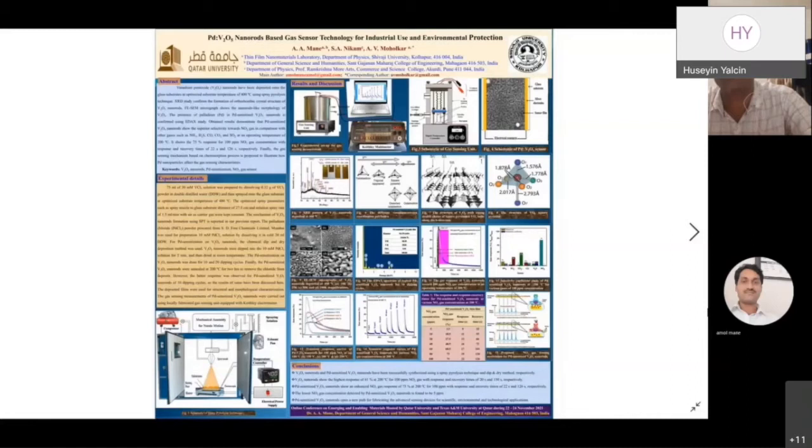In nitrogen dioxide, nitrogen contains one unpaired electron. After forming the covalent bond between nitrogen and oxygen, this unpaired electron in nitrogen is the reason why chemisorption of nitrogen dioxide gas is more likely in comparison with other gases. This unpaired electron in nitrogen of NO2 forms a bond with the surface oxygen of Pd-sensitized V2O5 nanorods and subsequently promotes the chemisorption.